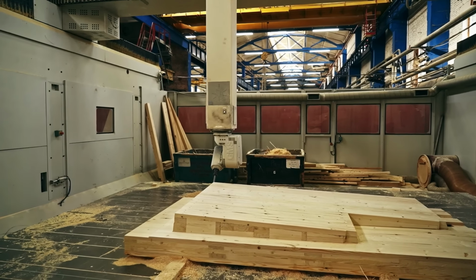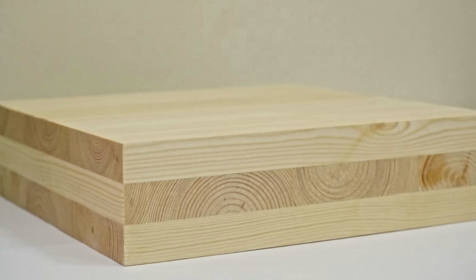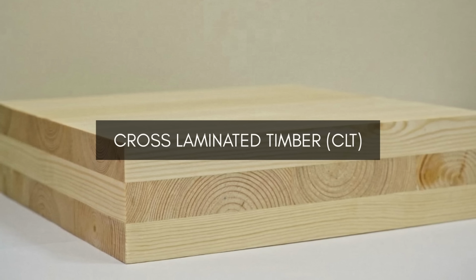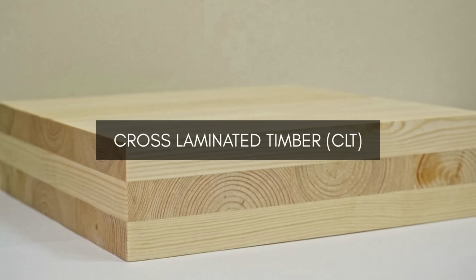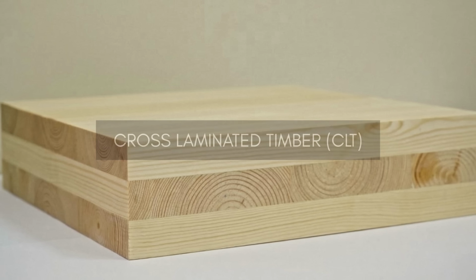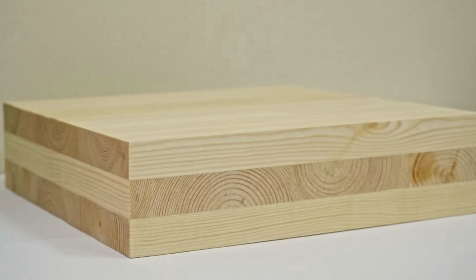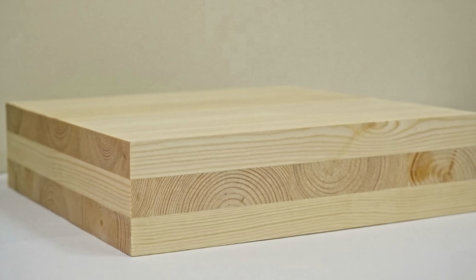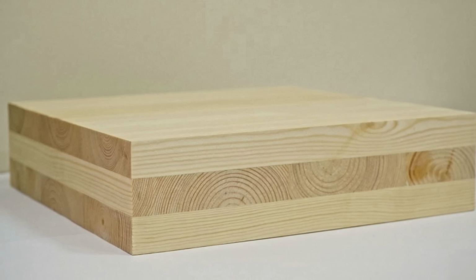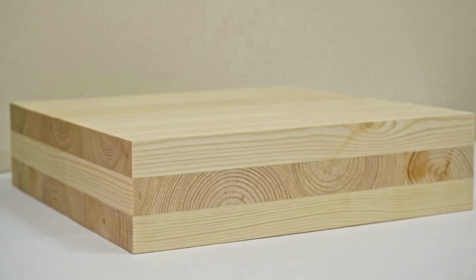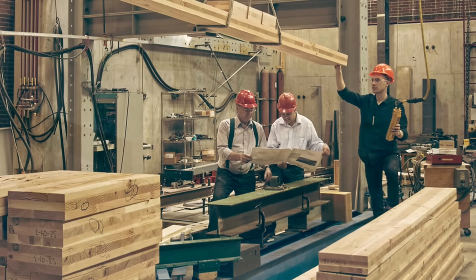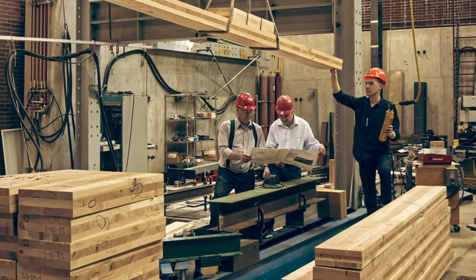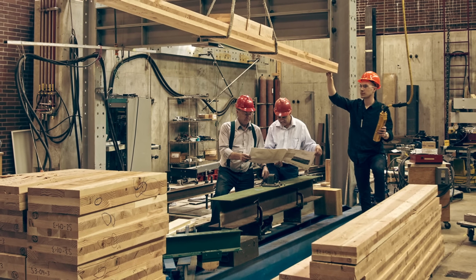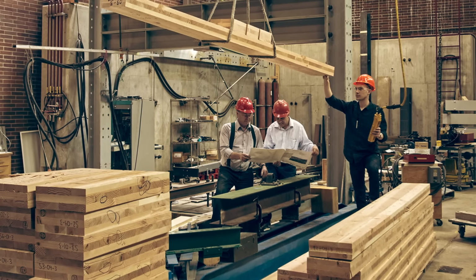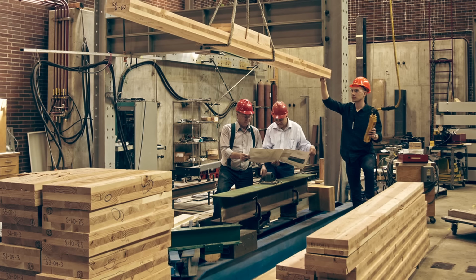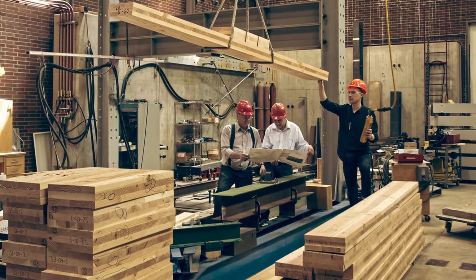By far the dominant product of the mass timber revolution is cross-laminated timber, or CLT, a prefabricated solid panel typically built from an odd number of layers of solid sawn lumber bonded under pressure with structural adhesives. Each alternating layer is oriented at exactly 90 degrees to the one adjacent to it. This cross-lamination simultaneously achieves two-way structural spanning capability and dimensional stability, as the negligible longitudinal shrinkage of the outer layers physically restrain the higher tangential and radial shrinkage of the perpendicular inner layers.